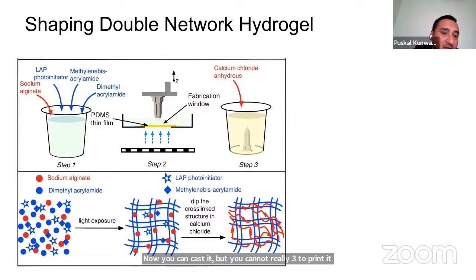Now what we came up with was this idea: we added acrylamide, MBA crosslinker, and photoinitiator LAP, which are required for photo cross-linking of acrylamide. Sodium alginate was just left there. We did not add calcium chloride, so that the ionic cross-linking doesn't occur. Then we photo cross-linked the acrylamide structure. This is only a single photo cross-linking at this point, which is still weak. The sodium alginate is still in the sample, embedded within the acrylamide, but the network is not cross-linked.